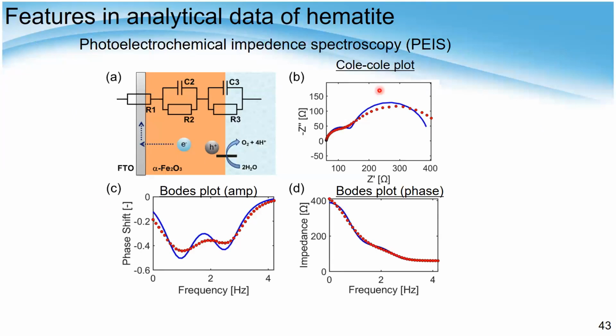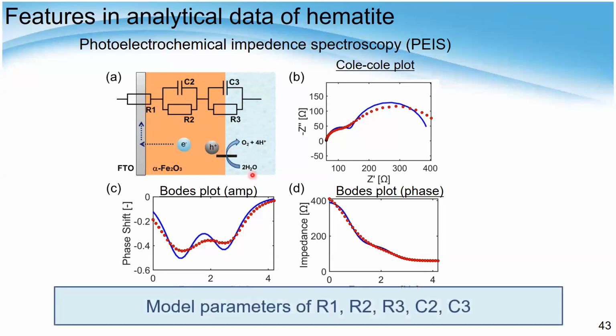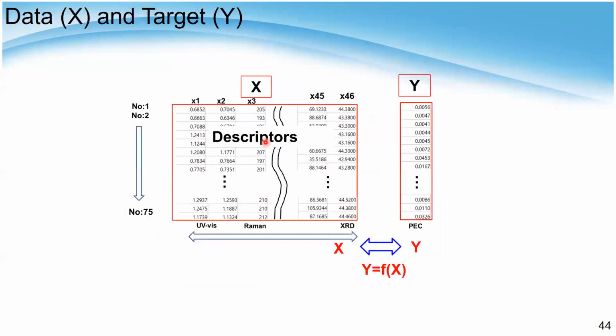And in this study, we added a more powerful analytical technique for the anode material, photoelectrochemical impedance spectroscopy, where during the light irradiation we can obtain the electrical parameters for the interface, bulk, and solution interface. This is the equivalent circuit we can model for these photoanode materials. So we can obtain the parameters of R1, R2, C2, and so on.